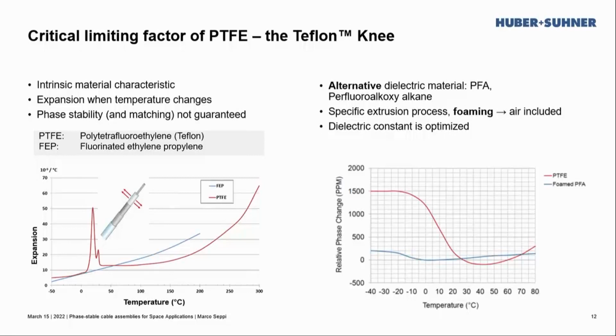As you see in the graph on the right side, the relative phase change in parts per million is remaining quite constant for PFA, on the contrary of what PTFE is showing in temperatures ranging from 0 degrees C to 40 or 50 degrees C. It's not only about using PFA as a material, it's also ensuring that the processing of the material and the extrusion characteristics are defined at best to maximize the performance. And in particular, foaming of the material is critical.